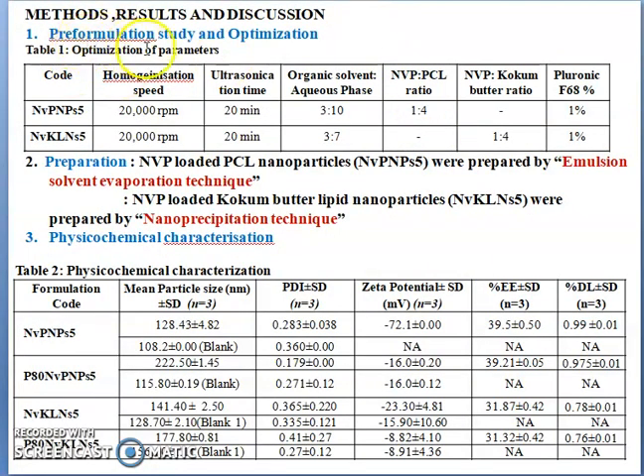Method, result and discussion. So first of all, a pre-formulation study was carried out to check the drug-excipient compatibility and identification of the drug and excipients, and everything was found with positive results. Optimization was carried out for homogenization speed, which was optimized at 20,000 RPM, ultrasonication time 20 minutes, organic solvent to aqueous phase 3:10, the drug to polymer ratio, drug to lipid ratio, and the quantity of surfactant. So the polymeric nanoparticles were prepared by the emulsion solvent evaporation technique and the lipid nanoparticles by the nanoprecipitation technique.